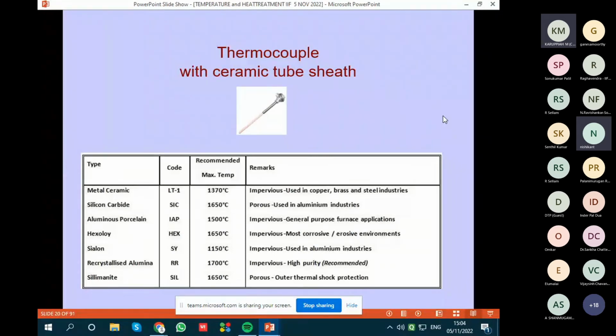There are different kinds of ceramic tubes. One is metal ceramic, silicon carbide, porcelain, recrystallized alumina. I'll always suggest going in for recrystallized alumina, because it lasts up to 1700 degrees centigrade. And metal ceramic or silicon carbide, they are prone to damage quickly. But recrystallized alumina or sillimanite are sheaths which will give a longer life.